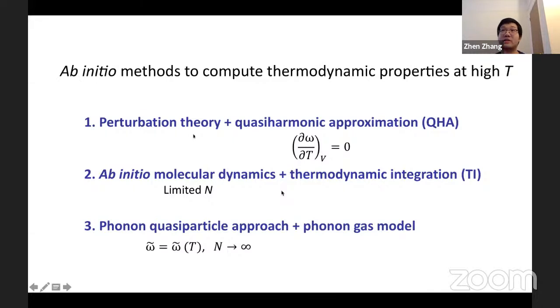The third method is the method I'm going to introduce in this talk, the phonon quasi-particle approach plus the phonon gas model. The phonon quasi-particle approach can give us explicitly temperature-dependent phonon frequencies with a sufficiently dense Q mesh in the thermodynamic limit. The phonon gas model uses the phonon spectrum to compute vibrational entropy, free energy, and thus thermodynamic properties.